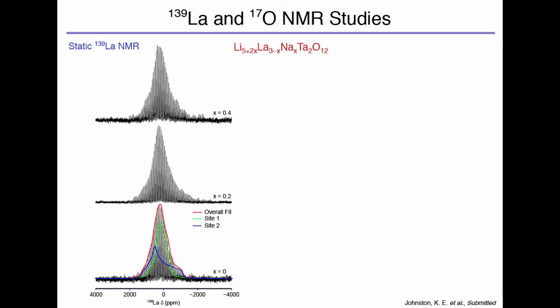So again, I said that we could indirectly look at where things are and what structural changes there are within materials. I did quite a lot of unusual NMR when I was a postdoc, and lots of people shy away from challenging nuclei and they don't want to do it because it's quite difficult. But actually, sometimes you get a lot of information from doing that. Here, we've done some static lanthanum-139 NMR, which is still quite niche and quite different. The idea here was, obviously, we think that the sodium is going onto that lanthanum site, so if we probe the lanthanum directly, does it tell us anything about the location of that sodium?